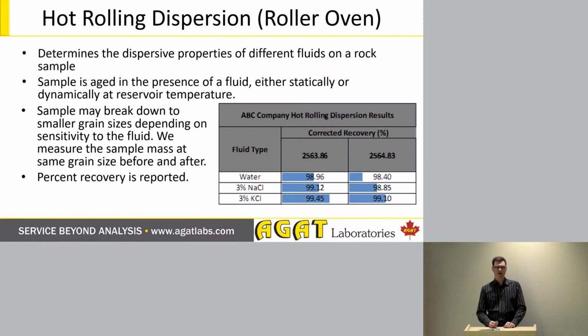So the first one is hot rolling dispersion, also called the roller oven. What we do is we mount the sample into a heatable turning unit that allows us to mix a fluid with the sample material at the same time. And we would do this with, for instance, clean water and water with multiple different additives. So it could be a water with a sodium chloride or potassium chloride salt. It could also be a water with a proprietary chemical additive provided by a drilling fluids company.